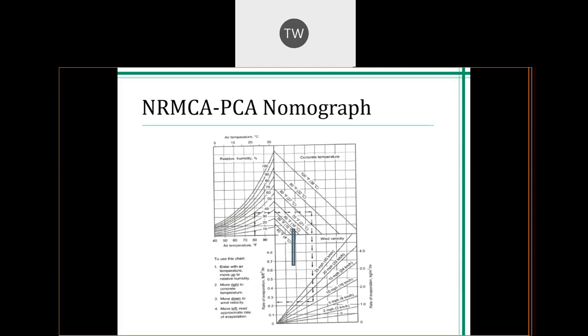In order to use this chart, you're going to need to follow the 4 steps outlined in this figure. I should mention, if the rate of evaporation approaches 0.2 pounds per square foot per hour, precautions against plastic shrinkage cracking are necessary.